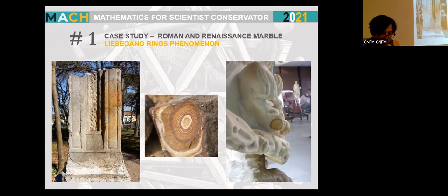damage of the substrate. Iron, in fact, tends to oxidize rapidly, giving rise to colloidal hydrate oxide that, in contact with porous material, such as carbonatic stones, may diffuse from its source, for example an iron linchpin, to the nearby stone mass, often with particular shapes, such as Liesegang rings.